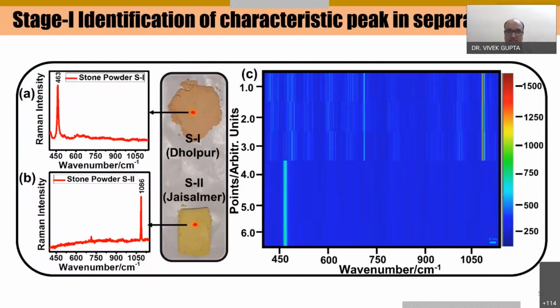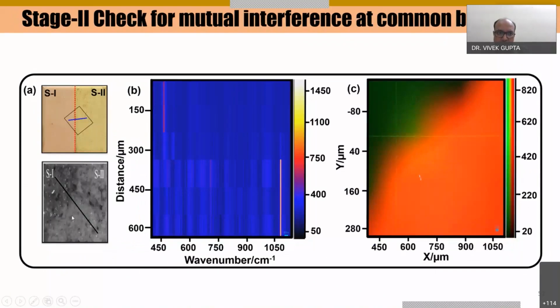So what we have found, in the first stage we were able to identify the individual peaks of each ingredient. We have taken two stone waves. One is the Dholpur stone waste, another is the Jaisalmer stone waste, and we have identified the characteristic peaks and selected the representative characteristic peaks: 463 centimeter inverse for S1 and 1086 centimeter inverse for S2 stone waste. And you can see a similar observation in the maps. You can identify how the boundary between the two different materials is changing. Then we made a common boundary and took the line measurement, and you can see at the upper side you can identify one material, and at the bottom side you can identify the other material. The top one is S1 and the bottom one is S2.